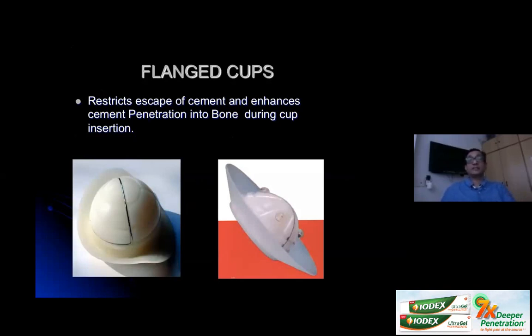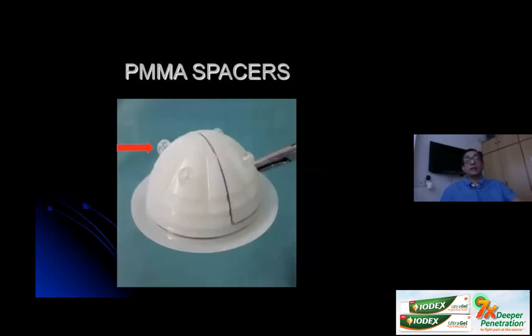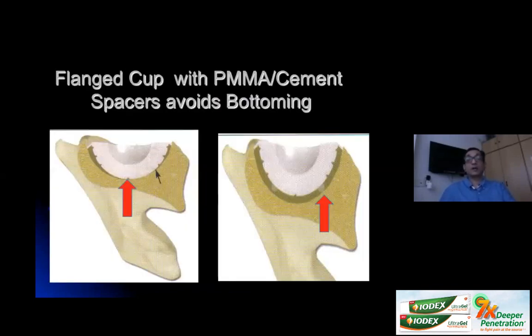Again, the flange cups have done well because the flange cups restrict the escape of cement and enhance the cement penetration of the bone and lead to better fixation. This is a new feature that has come up. Nowadays, the cups have methyl methacrylate spacers, which again help you attain a good cement mantle and prevent bottoming. So by using these kind of cups with these kind of spacers, we can achieve good uniform cement mantle rather than the bottoming out which we saw once upon a time.